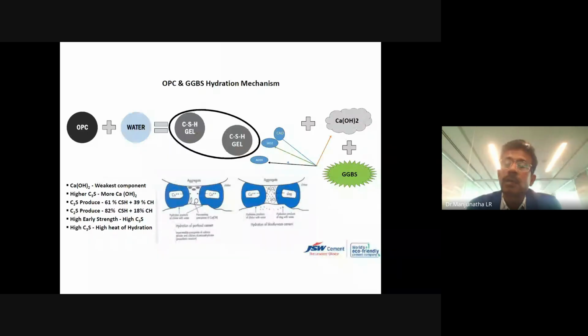The advantage is that when we add GGBS to the concrete matrix, it has three components: alumina, silica, and calcium oxide. Calcium oxide directly contributes as a cementitious material in enhancing the CSH gel. Then alumina and silica work with calcium hydroxide as a pozzolanic material, converting it further to CSH gel. Hence, we have a robust concrete structure which is highly durable. Increased durability, increased long-term strength, and also better particle packing. These are the various benefits you get by adding GGBS to concrete. I can show you here, this is without GGBS. A lot of calcium hydroxide is there. And here you can see a slag-based concrete matrix, where the interfacial transition zone is always occupied with the hydrated product, CSH gel.